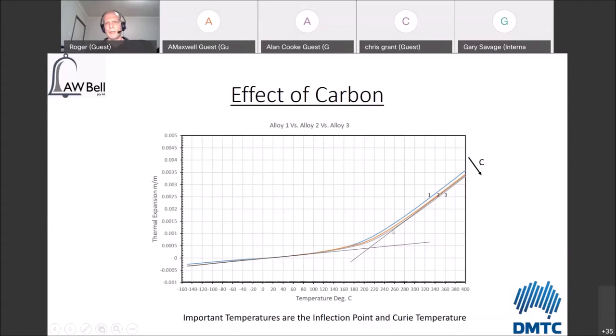There are a lot of different ways of measuring the Curie temperature. You can approximate it based on these curves, and approximation is all you really need, because the Curie temperature is related to the magnetism of the material. This is outside of the temperature range that we're interested in, and the magnetism of the material isn't necessarily a problem for us. What we're interested in is all of this low temperature behavior up to the inflection point. So that's the effect of carbon.